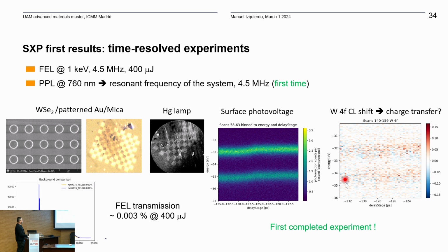And then in the last remaining time, we measured the shift of the tungsten 4f, and there seem to be some indications of charge transfer, but the data analysis is still ongoing. Something that is very important is that the FEL transmission that we need is very low, 0.003% at 400 microjoules. However, the high repetition rate of European XFEL is necessary to realize this type of experiment.